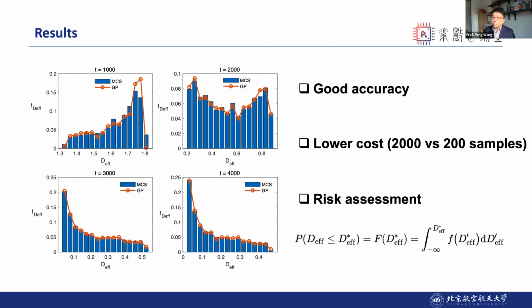And here we present the probabilistic density function, which characterizes the uncertainty of our prediction via 4 snapshots of the effective diffusion coefficient at time step 1000, 2000, 3000, and 4000. And as we can see, the blue histograms are the solution from 2000 Monte Carlo simulations, which take months to do. And the red dotted lines are actually from our Gaussian process predictions.